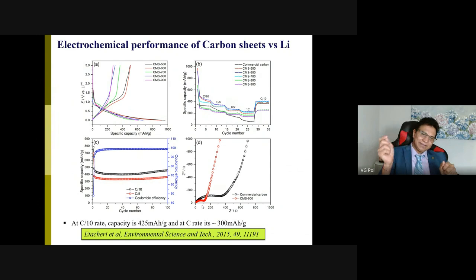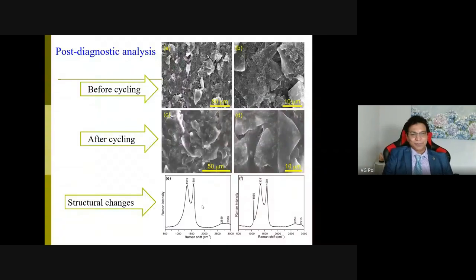Now, once inside the battery, we also wanted to see what happens to those sheets when we cycle, or charge and discharge, the battery for hundreds of times. The top panel shows that these are the sheets with some binder we put inside. And after lots of cycles, charging and discharging, these materials sustain inside the battery, do not decompose, do not degrade. So this sheet-like morphology remains like a sheet.